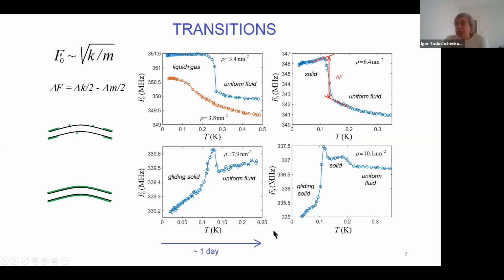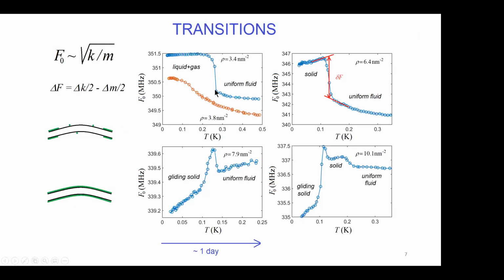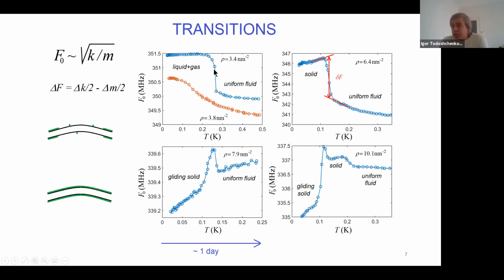Now I go to results. Basically, we saw 4 kinds of transition. At lower densities and at lower temperature, there is a liquid-gas coexistence. In this coexistence, the liquid clusters are mostly on the ends of the tube. That's because the ends of the tube are quite rough, and there is always some amount of solid helium, and then the liquid tends to attach to this. When we warm up above the critical temperature, the liquid-gas coexistence transforms into a uniform fluid, and then these liquid clusters arrange uniformly over the tube, and the effective mass of the tube increases. That's why there is a sharp decrease of the resonance frequency.